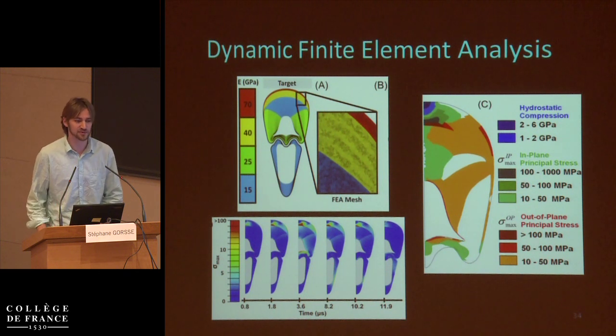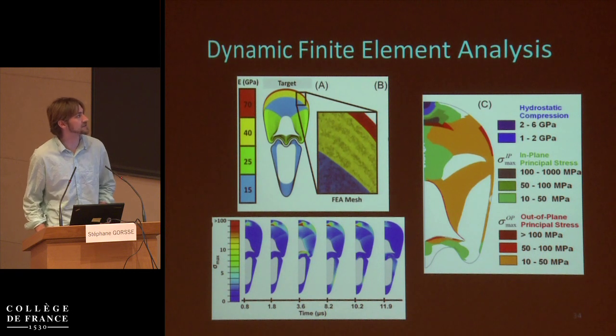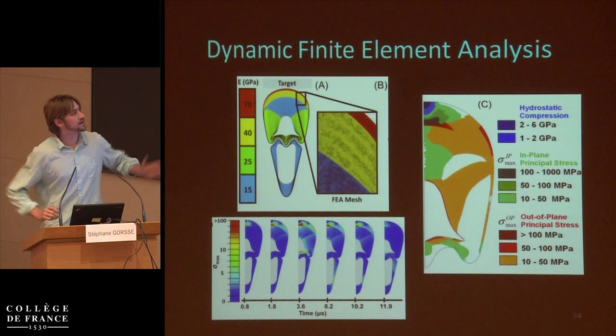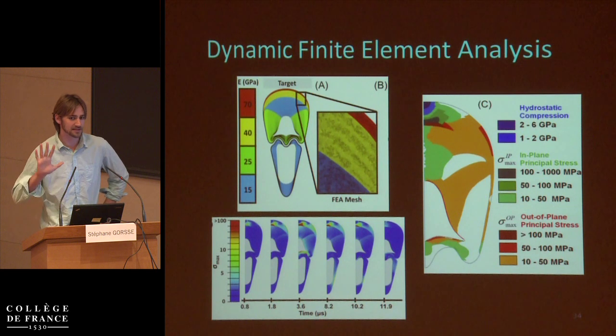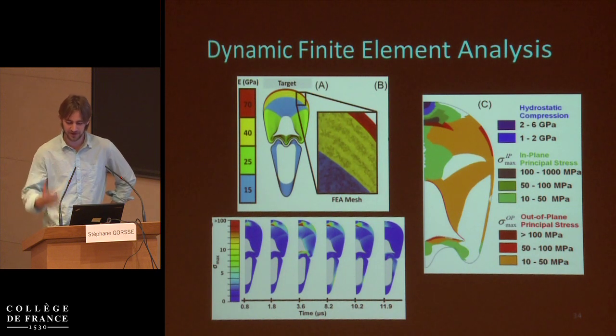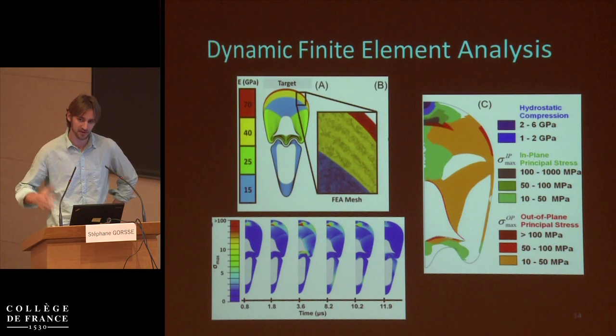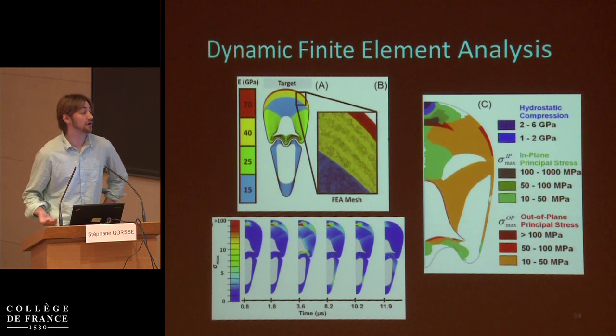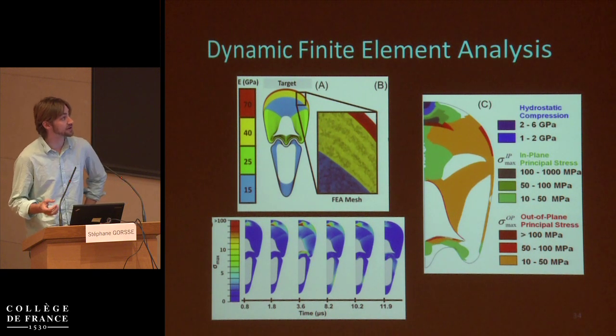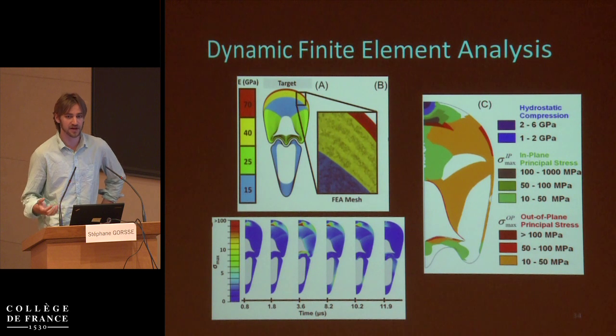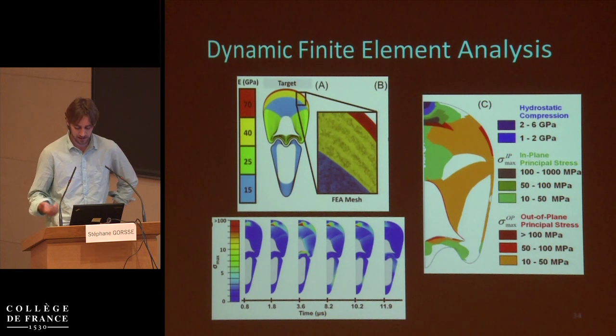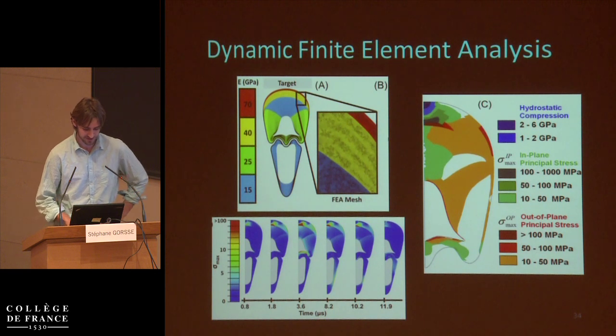So that's clearly impossible. And what I think this tells us is not that we've got it right, but that if we put in just the simple basic values that nanoindentation spits out and then plug those into the simulation, we're clearly wrong. And so this proves that the microarchitecture is important and somehow having to distribute these forces, otherwise it would be much more incredible than it even is.